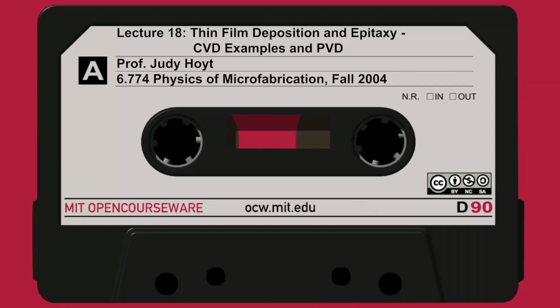Polysilicon is the most commonly deposited material by LPCVD. It's the gate in CMOS. We've barely scratched the surface of poly. I think it's a reasonably good topic if you want to do one of your reports. You need to optimize the temperature and the pressure and the exact conditions to get the right grain structure so you can get diffusion of dopants properly and good electrical activation in the grains.